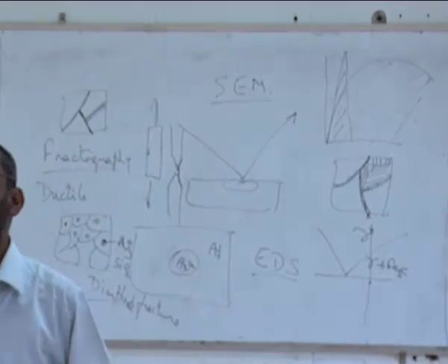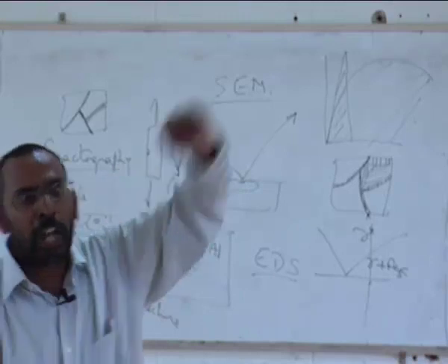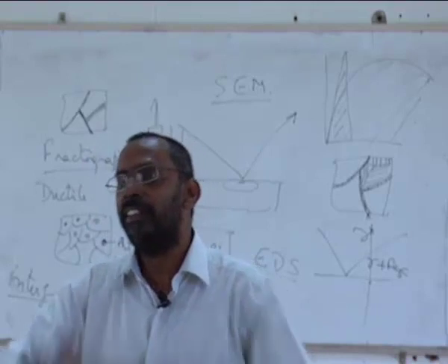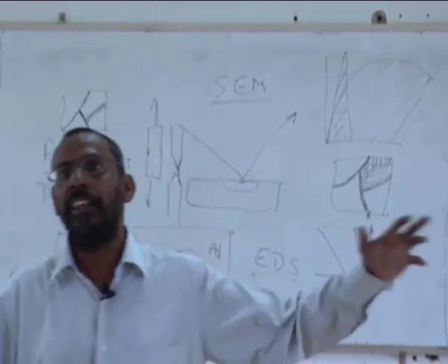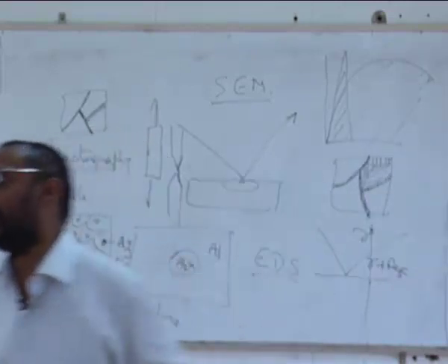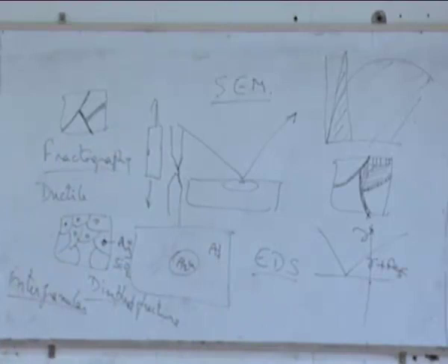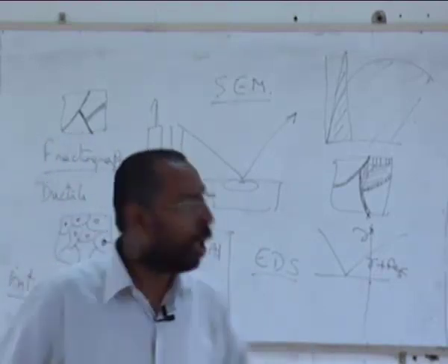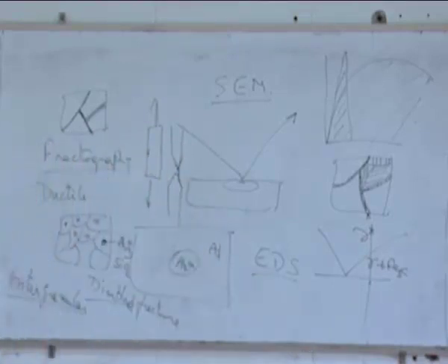And when you are flying, there are stresses. Why are there stresses? Because outside it's all vacuum, inside there is a pressure. So because of this pressure, the crack starts propagating. Whenever you apply pressure, the crack propagates. So it can fracture, and once there is a fracture at some place, obviously the air inside rushes out, and the whole thing fractures. So this is how people were able to prove that actually it was not because of any terrorist attack and things like that. So this is all possible with a microscope like that.